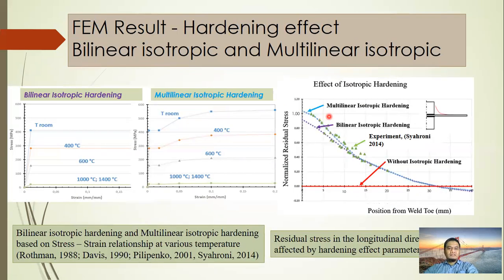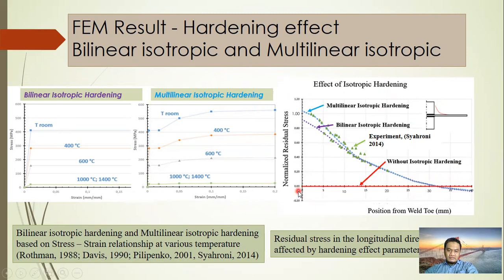Next, we need to apply a hardening effect in the simulation. We use isotropic hardening, with the stress-strain relationship at various temperatures based on data from Rothman, Davis, Pilipenko, and Syahroni. Without isotropic hardening, there is almost no residual stress. With bilinear isotropic hardening, results are slightly below the scatter data. The best-fit curve is achieved with multilinear isotropic hardening, as shown in the figure.